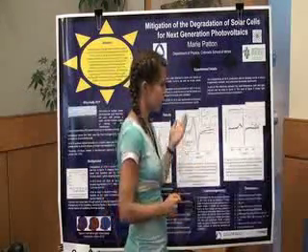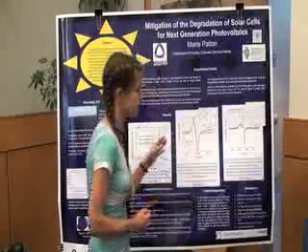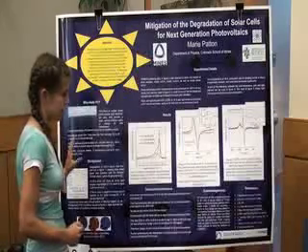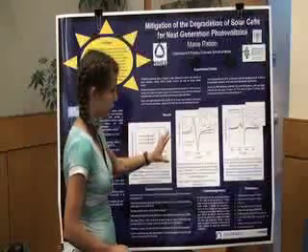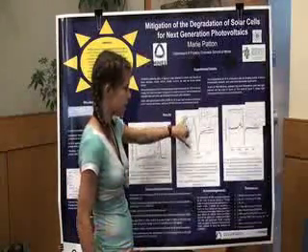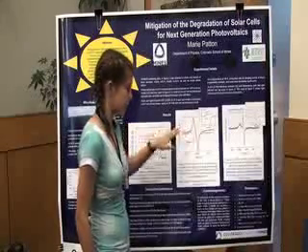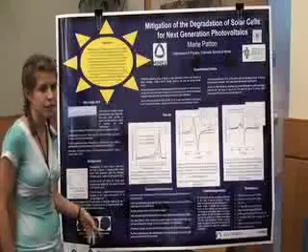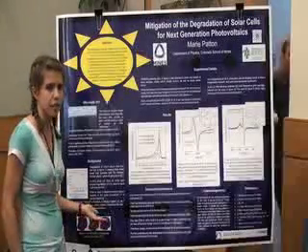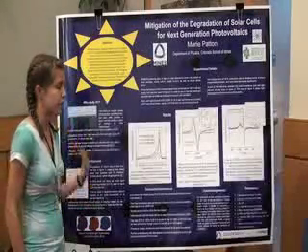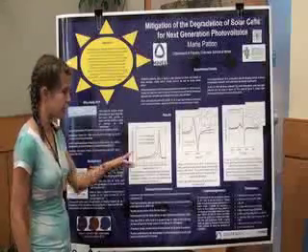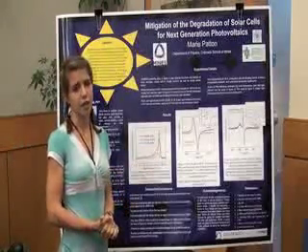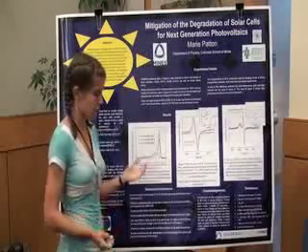What we determined is that the amorphous degrades a lot in the sunlight, and the 90% crystalline also has a lot of defects because it has a lot of grains, and there's about one defect per grain on each of these crystallites. So the 50% mixture, which is this one, is probably about the best for photovoltaic modules because it's the best of both worlds.